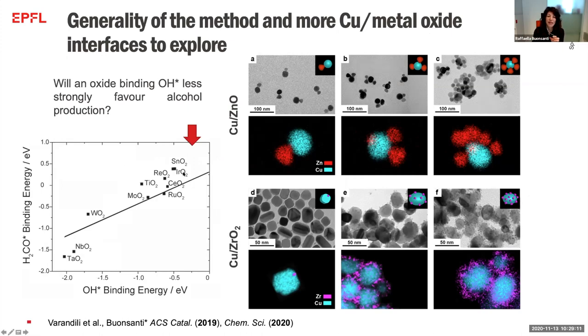So now the idea was to move towards oxides that don't bind the oxygen too strongly, to eventually be able to evolve, for example, methanol instead of methane. And the synthesis that Benaz developed is really applicable to other copper metal oxides. And so now she's playing around with them and seeing if we can switch the selectivity from methane to methanol. So interfaces are important,